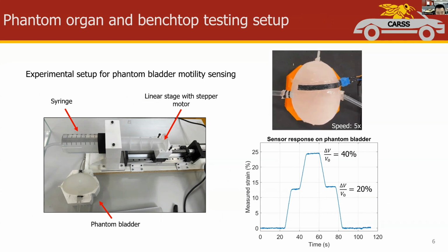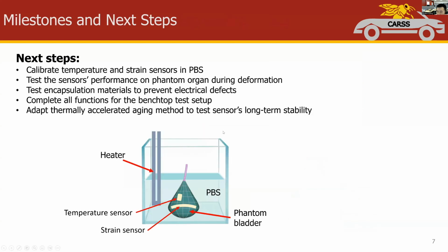When the bladder expands and contracts, the capacitive strain sensor can clearly measure the surface strain induced by the volume change. From the data shown at the right corner, the capacitance can also return to the initial value right after the bladder returned to the initial state. So that's our current progress.